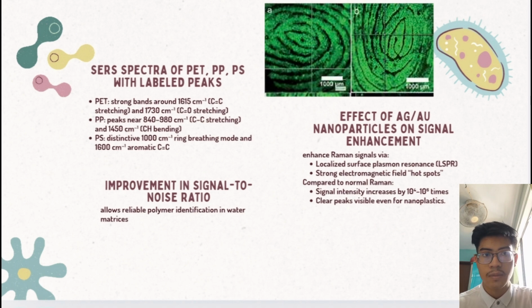SERS substrates. These enhancements occur due to localized surface plasmon resonance, which generates strong electromagnetic field hotspots near the metal surface. Compared to conventional Raman spectroscopy, the signal intensity increases by approximately 10 to the power of 4 to 10 to the power of 6 times, allowing clear detection even for nanoplastics. As a result, the signal to noise ratio is greatly improved, enabling reliable polymer identification directly in water matrix.